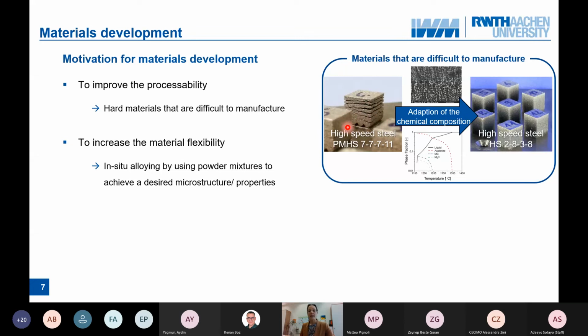You see a lot of cracks, and we adapt the material, the chemical composition, to get a material that can be processed crack-free. And therefore we need to have a very close look into the microstructure to find the reason for cracking. In that case, it was, for example, the high tungsten content in the material, and the tungsten forms strongly connected carbide networks, and across these networks the cracks were able to go through the material very fast and easily. So, accompanied by thermodynamical simulation, we do material adaptation here.